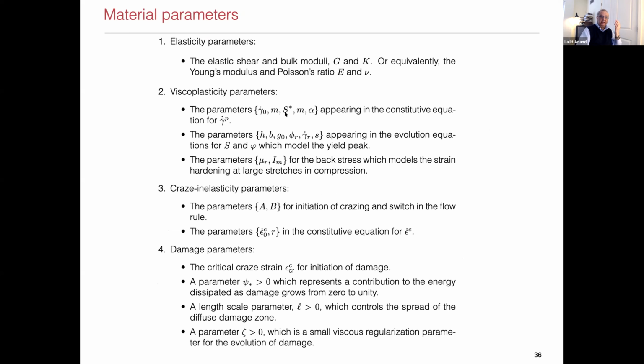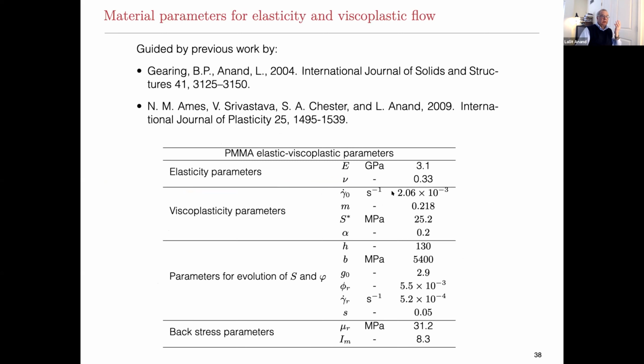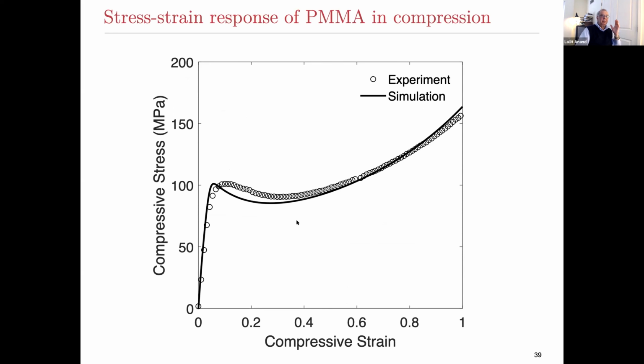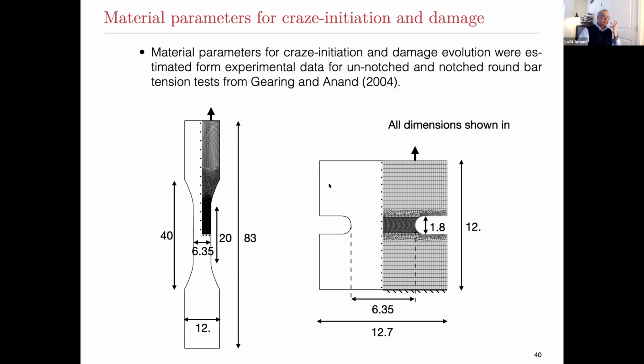There are some material parameters that are needed in the theory. The material parameters for the plasticity, let me just show you what they are. Okay, so there's experimental data, actually some work that I had done going back to 2004 on PMMA and polycarbonate. Based on that, we can determine the parameters for the plasticity part. Again, please don't waste too much time trying to understand the numbers. But in the end, for the compression test, you can approximate the elasticity, the plasticity, the yield peak, and the strain hardening. Okay? That's PMMA in compression. But now we want to calibrate the material parameters for the crazing and the craze breakdown and the like.